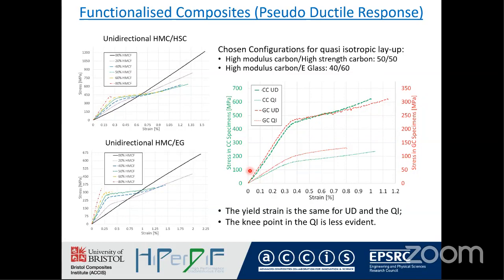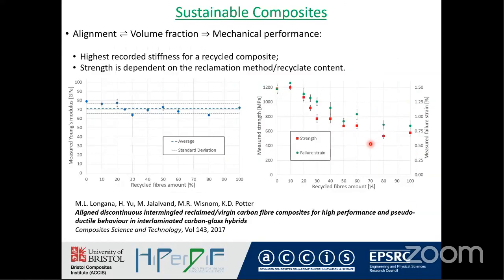So in this case, we've selected one example of each. Here's the unidirectional response for the carbon and the glass in red. And here the corresponding responses for the quasi-isotropic layout. And as you can see, in both cases, the yield strain is the same for both the unidirectional and the quasi-isotropic. The knee point is somewhat less evident in the quasi-isotropic, but nevertheless, as you can see, there's a clear plateau before the material undergoes failure. So the concept of a material that fails somewhat more gracefully is shown to be achievable.